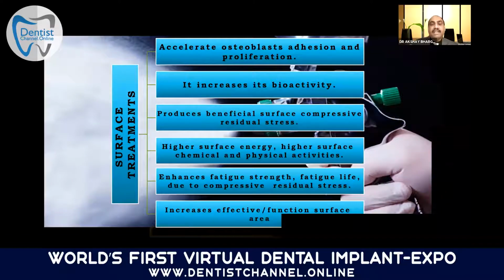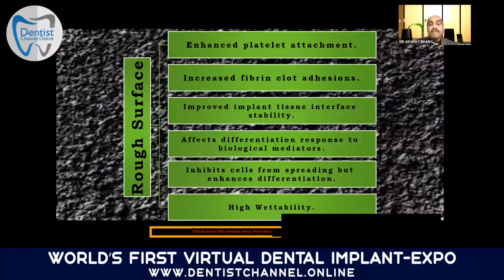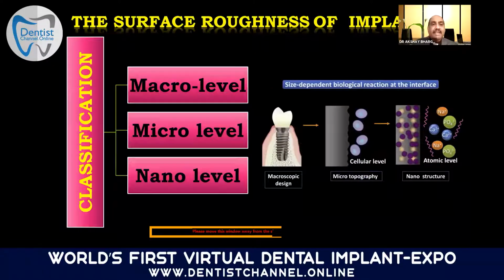So, the roughness. Now what happens when we create a rough surface on an implant, which, as I told you, can range from less than 0.5 microns to greater than 2 microns? Enhanced platelet attachment, increased fibrin clot adhesion, improved implant tissue interface, and it affects the differentiation response to biological mediators. It inhibits cells from spreading but enhances differentiation. And most important, though last, is high wettability. The more hydrophilic, the better, because the whole body is composed mainly of fluids. So even wound healing takes place by a lot of fluid interaction and vascularity.